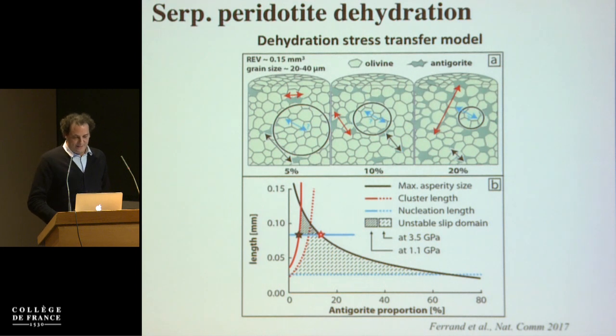the interesting thing is that one of the conundrums is that it has generally been said that the serpentine dehydration would trigger dehydration embrittlement, and this dehydration embrittlement relies on the reaction producing water, and this water actually takes more space than the porosity that is created by the reaction. So basically, it's some sort of a hydrofracturation.